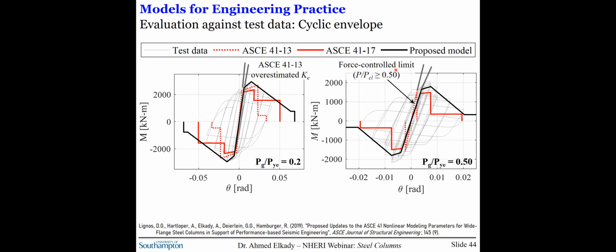With respect to the current ASCE 41 standard, again, as I mentioned, the proposed model overall appears to fit the test data better. For instance, the post-yield hardening slope and the gradual decrease in the flexural strength in the post-buckling region reflect the actual behavior better.